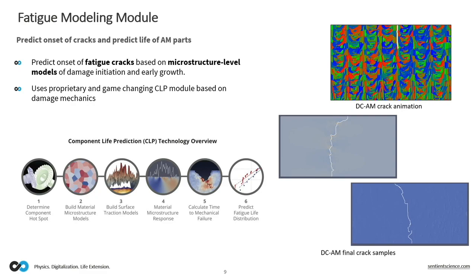Or even if they are computational, they are based on linear fracture mechanic. This is based on damage mechanic, and its biggest advantage compared to fracture mechanic is that you do not need an initial crack to start your simulation and see how that crack is going to get to the failure, which is against what you need in fracture mechanic, right? In fracture mechanic, you need an initial crack, and then you're simulating how long it's going to take for that crack to become critical.